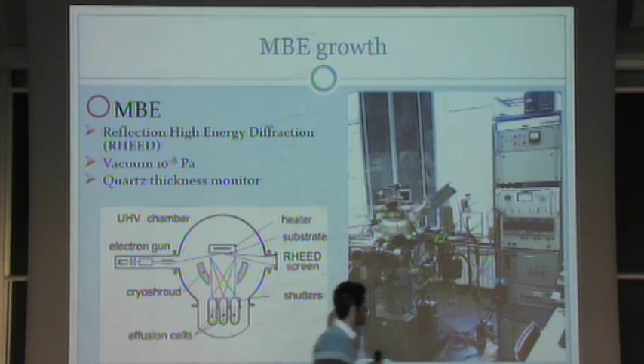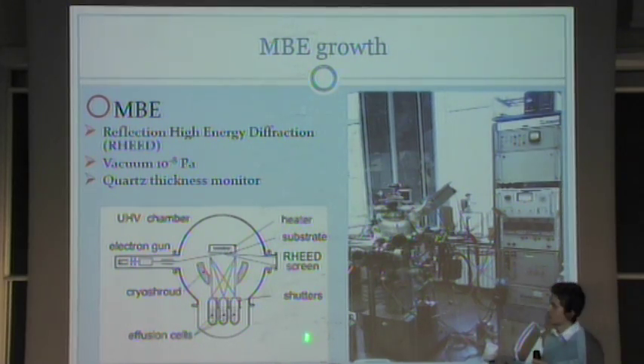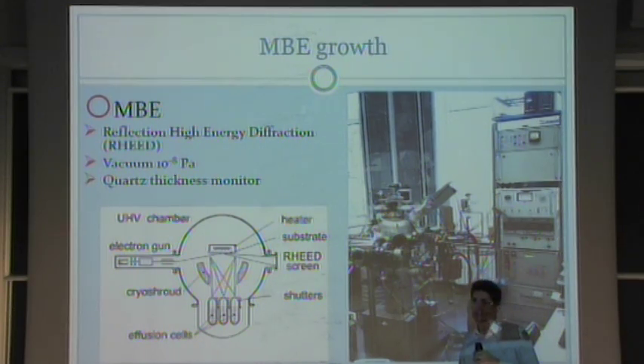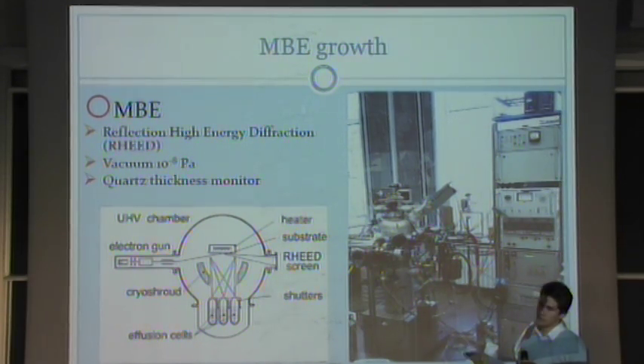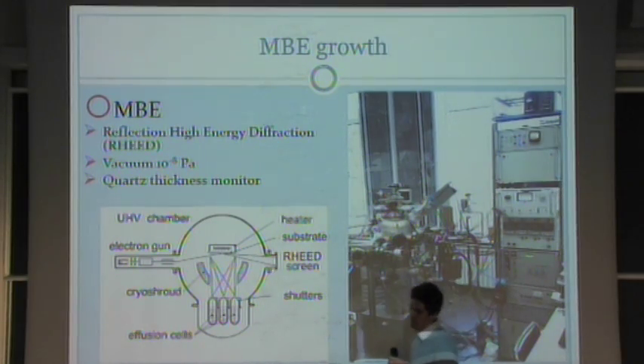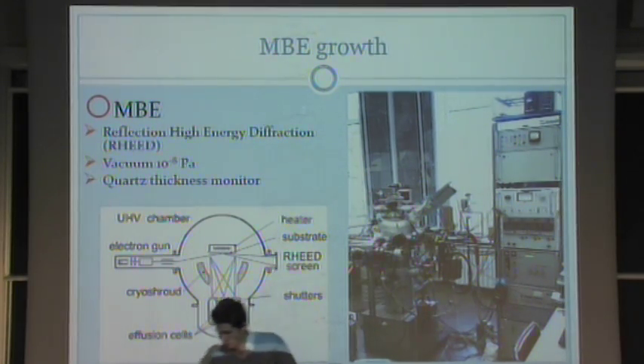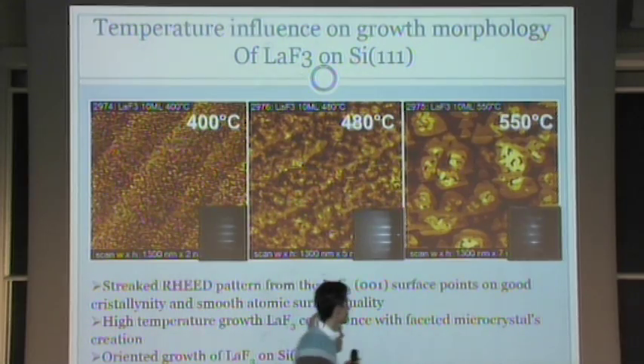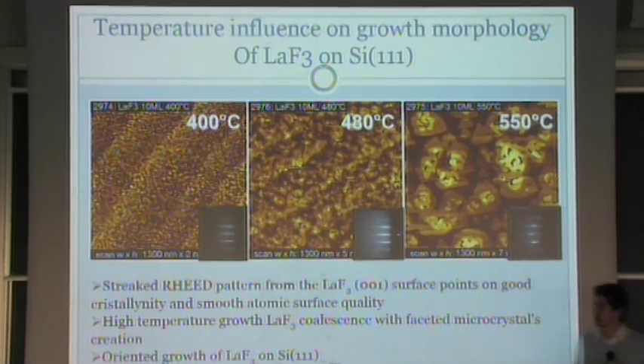And how we create these sort of structures with molecular beam epitaxy. So here is the chamber of growth in St. Petersburg, and how it works. You put the very pure material in an effusion cell, you heat it, and the material evaporates on top of the substrate in the middle of the chamber, and then you can analyze the structure with different techniques, such as diffraction or atomic force microscopy. And here, for example, there are several structures of the big series of our